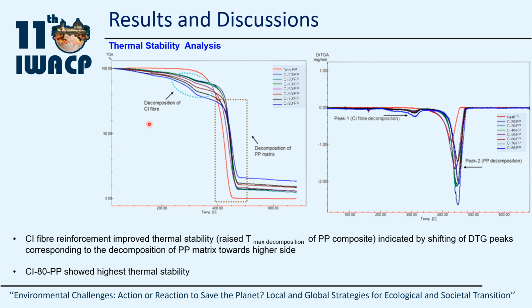The left side shows the TGA curve for the composite materials, in which the red curve shows the TGA curve for neat polypropylene, which we can see indicates single stage degradation. Whereas after inclusion of Canna indica fibers, we can see there is a shift in the TGA curve for all the 7 mix ratios, with the maximum in case of CI-80PP, which is 80% fiber loaded neat polypropylene matrix. A similar change has also been reflected in the DTG curve. A maximum of 21-degree rise was observed in case of CI-80PP composite, which indicates its highest thermal stability among the 7 different mix ratios.